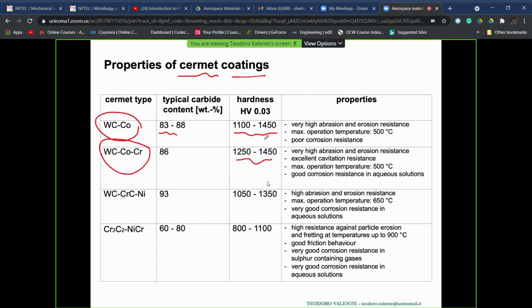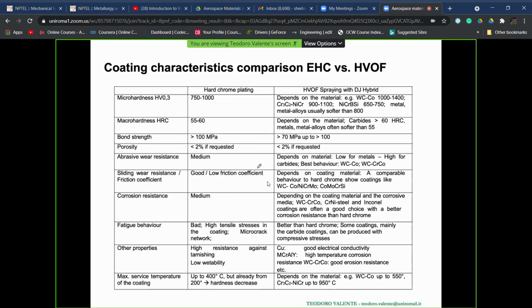And if we just have a look at the hardness values, we are able to reach, apart from the last one, which is not used for this purpose, values which are the same and sometimes also higher than those obtained with hard chromium, based on hexavalent chromium. Here you have a table just to summarize one and the other solutions: chrome plating and HVOF.